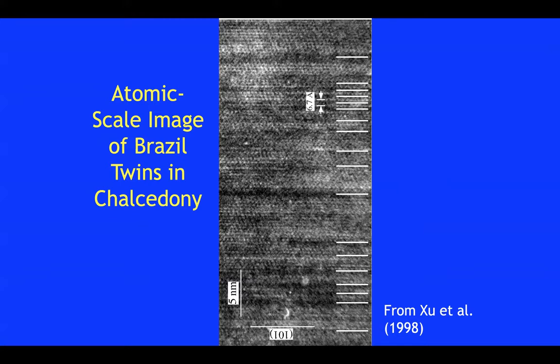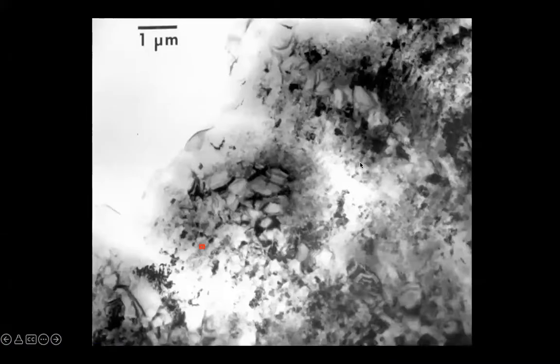He's a mineralogy professor at the University of Wisconsin, who used a very high magnification TEM to get high resolution images of chalcedony, and showed indeed, where you see these white bars, again, where's my arrow? These white bars here are Brazil twin boundaries. And so this is essentially Brazil twinning at the atomic scale. So we've got these regions that are densely Brazil twinned, alternating with regions that are not very densely Brazil twinned, just as we had inferred from our X-ray diffraction data.